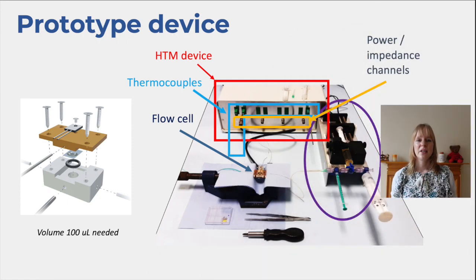But here you can see a picture of what this setup looked like. Basically it's a big box. What's in there is a system that can first of all measure the temperature. We want to have something that can control the temperature, which we do with a feedback loop and a power source which can apply a certain voltage. And then we also want to make sure that we have a Bluetooth connection so we can get our data, in this case on a laptop. And all this was controlled with LabVIEW software.